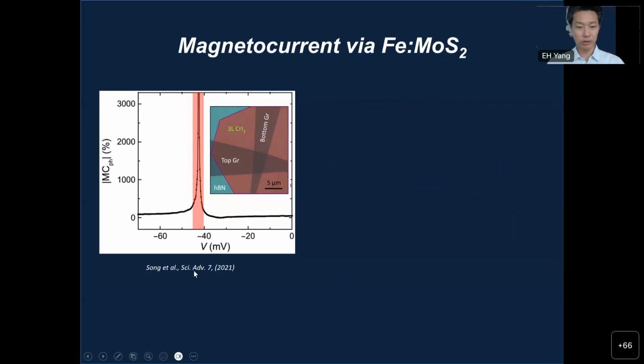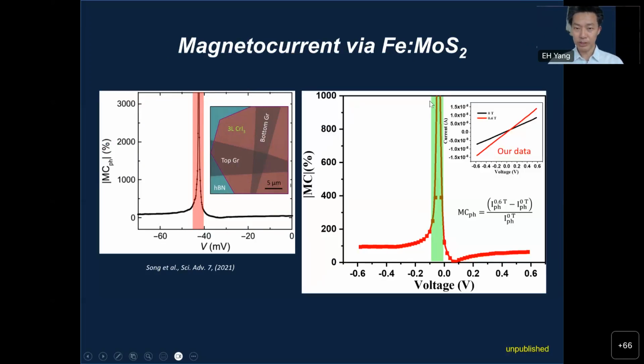This is published in Science Advances. Okay, it's a high impact journal, as you know, and it's right next to the journal Science, and that basically shows they use this 3-layer chromium triiodide here, and basically then show this sharp peak. So we did similar using our material. As you can see, we have similar values here. Of course, there are a lot more things to do to further understand, but you can clearly see the enhancement of the forward current under the application of the magnetic field due to the spin current. And I wouldn't say spin current because it's a little controversial. We need further work, but this is magnetocurrent.